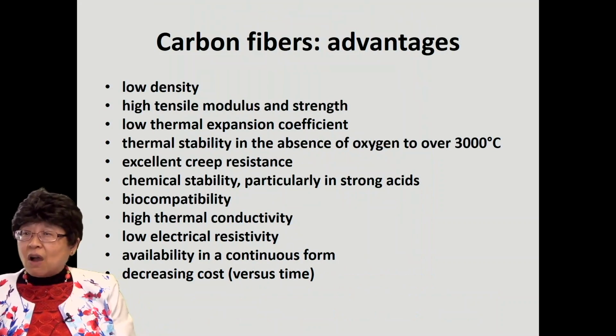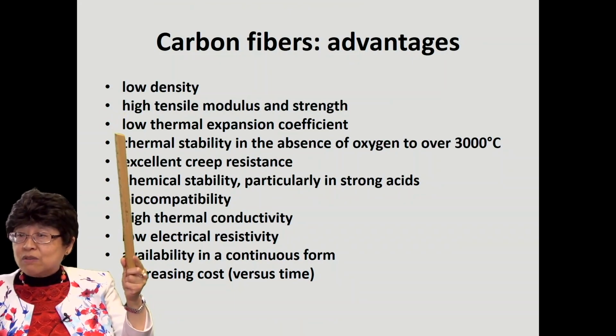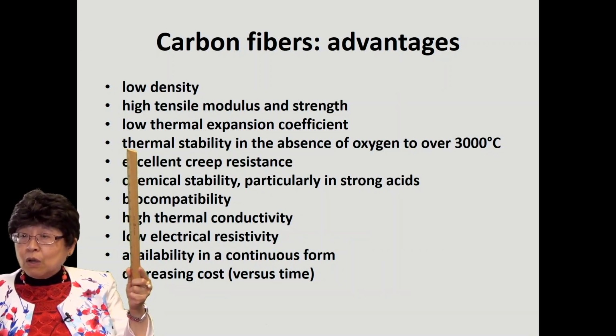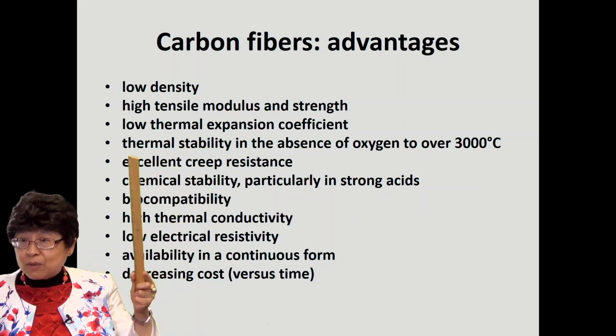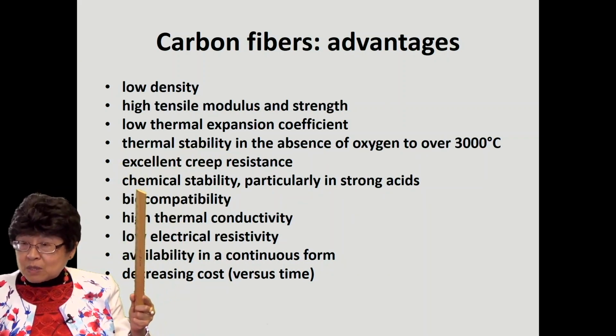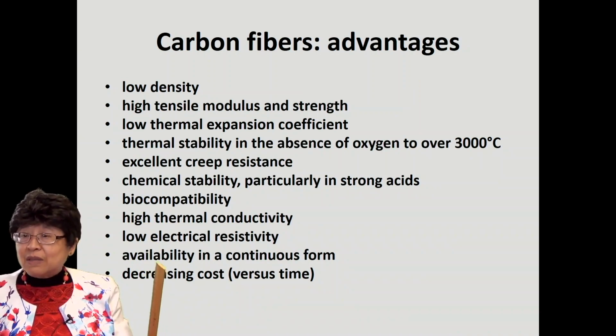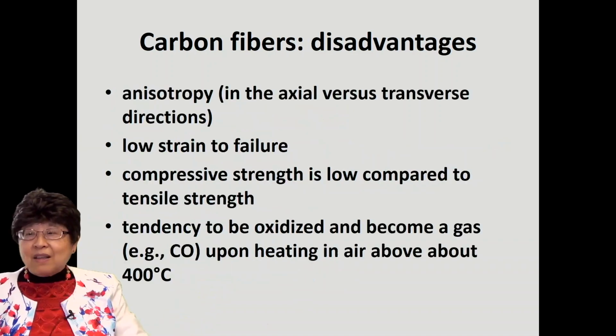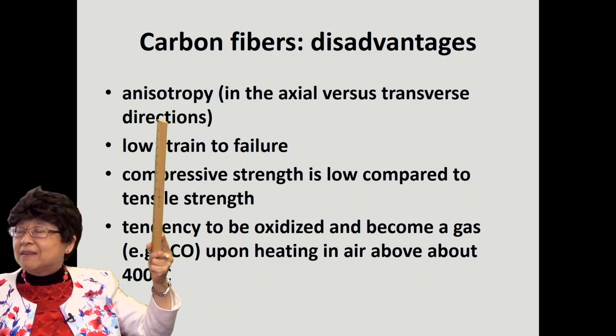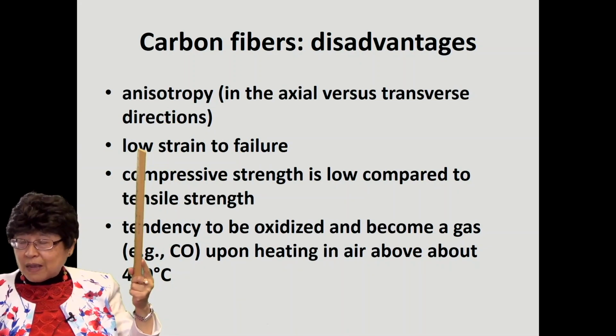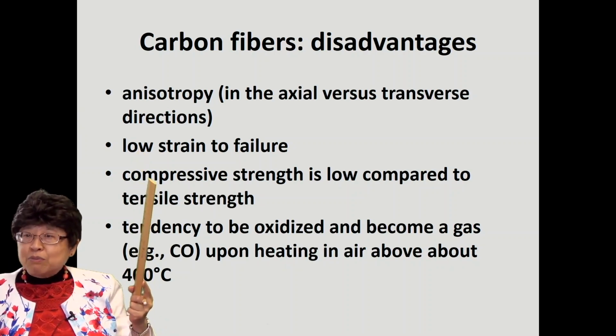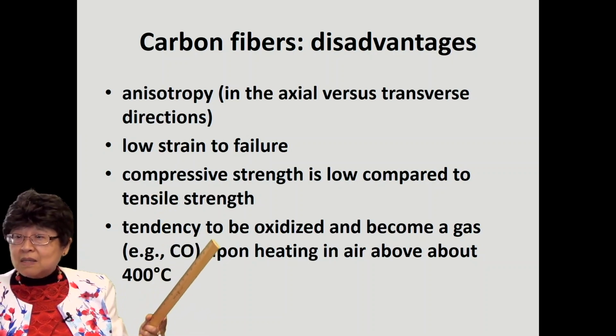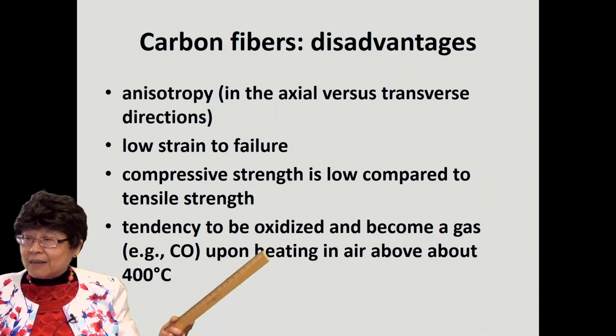There are numerous advantages of carbon fibers: low density, high tensile modulus and strength, low thermal expansion coefficient, thermal stability in the absence of oxygen to over 3000 C, excellent creep resistance, chemical stability, particularly in strong acids, biocompatibility, high thermal conductivity, low electrical resistivity, availability in a continuous form, and decreasing cost over time. But there are still some disadvantages. The anisotropy, the axial direction versus the transverse directions being different in property. Low strain to failure, and it's still kind of brittle. Compressive strength is low compared to the tensile strength. And also the tendency to be oxidized and become a gas, such as CO, upon heating in air.